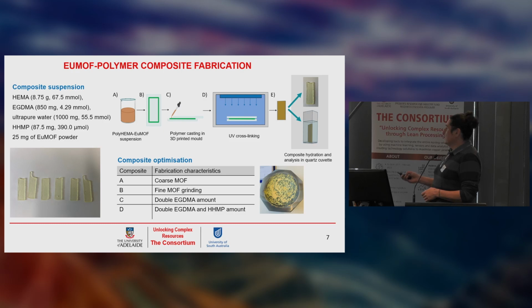So Piotr made various different compositions, so slightly different formulations, and assessed how they performed. So there's four different, I think he did more than this in actual fact, but there's four here. The first one where he had a coarse MOF, so that means the MOF isn't ground, the particles are quite large. One where he finely grinds the MOF, and it actually changes colour. So it starts off as orange, and as you grind it more and more, it becomes a pale yellow, related to the size of the particles. Composite C was the same base polymer formulation, but more heavily cross-linked, so a more rigid polymer network. And then composite D was, again, a more rigid polymer network with additional cross-linker to really make it hard and tough.